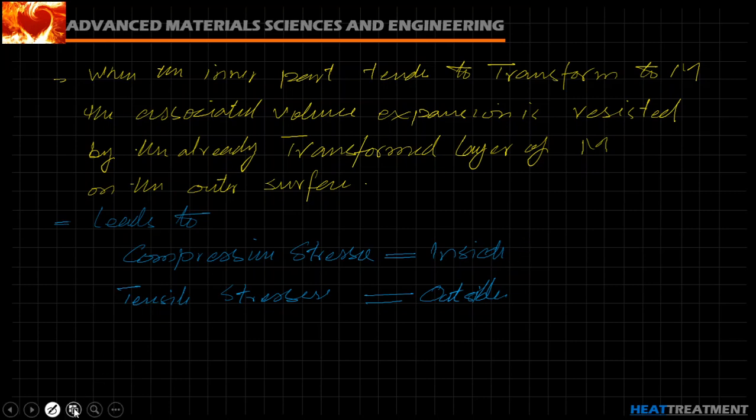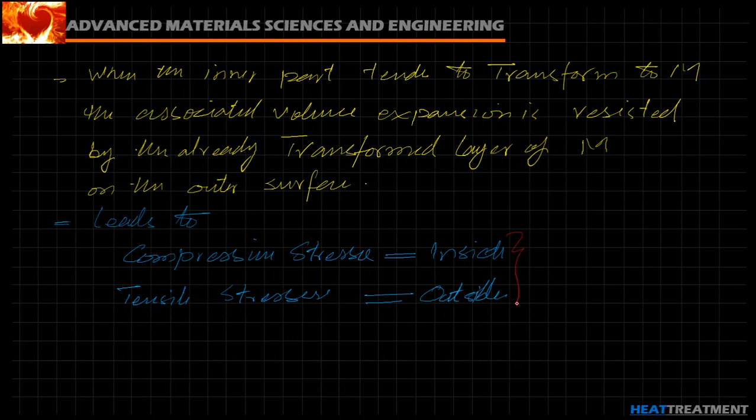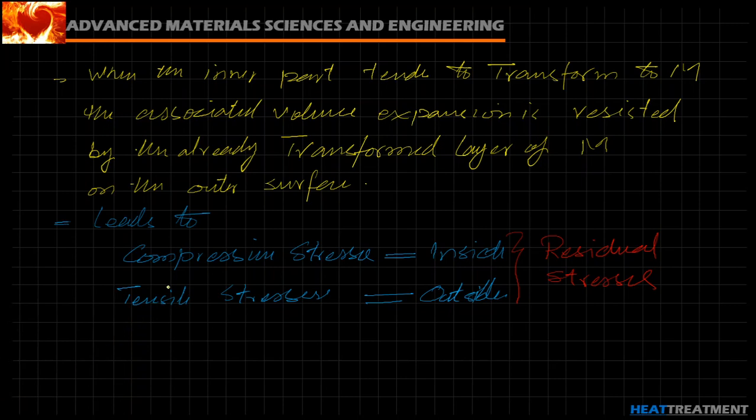And these stresses are termed as residual stresses. Now in general these tensile stresses are very dangerous, which causes the quench cracks.